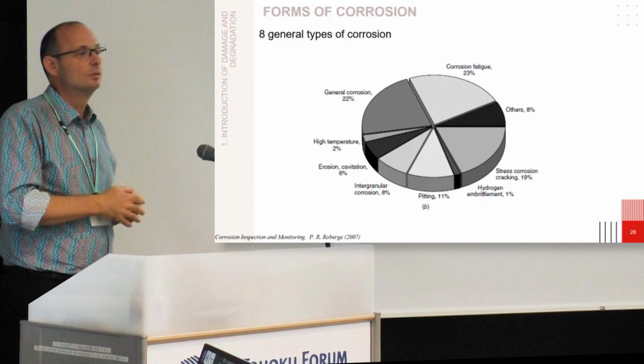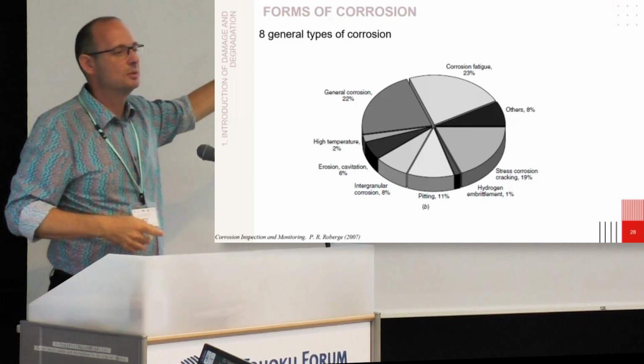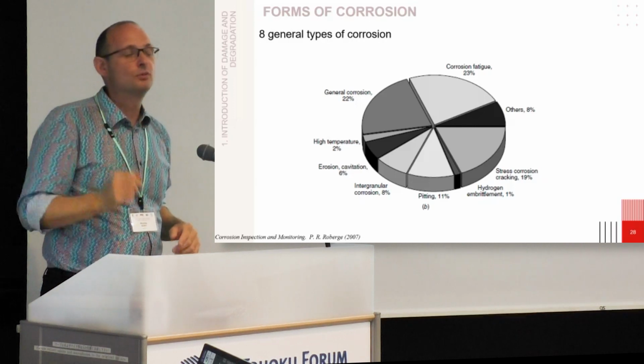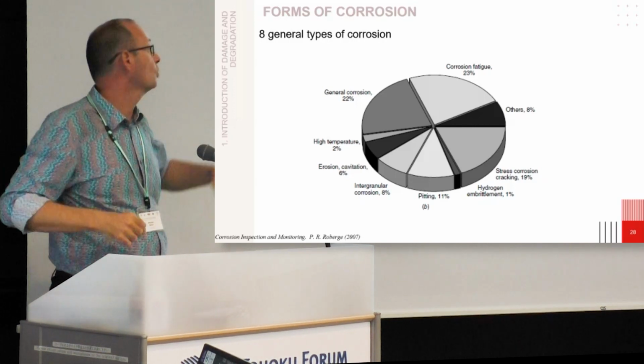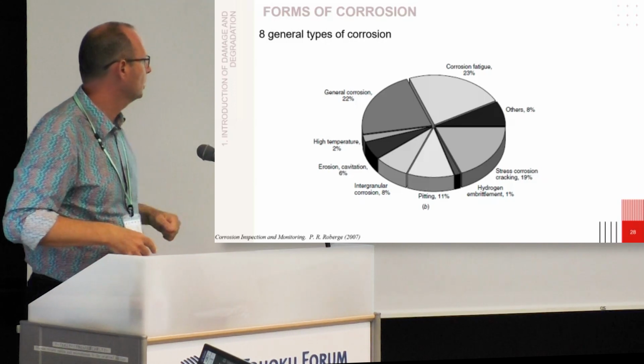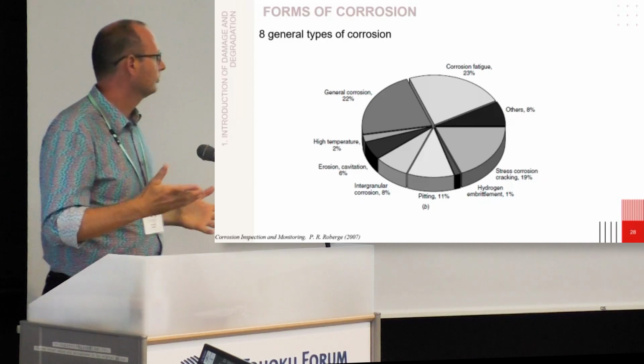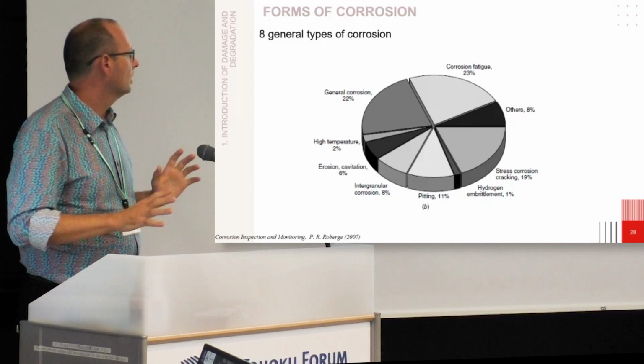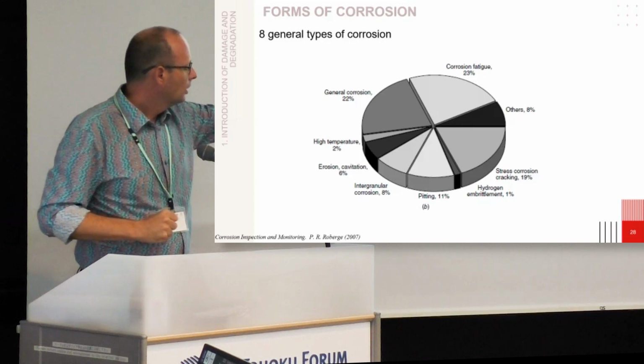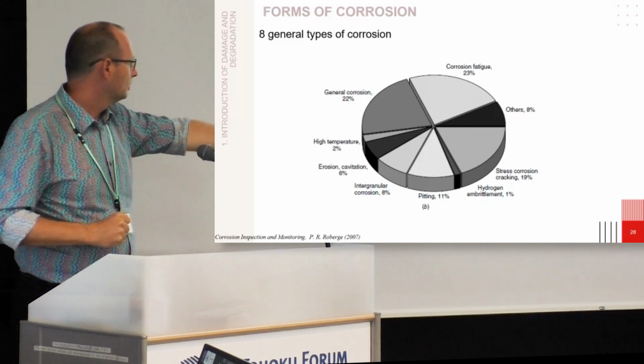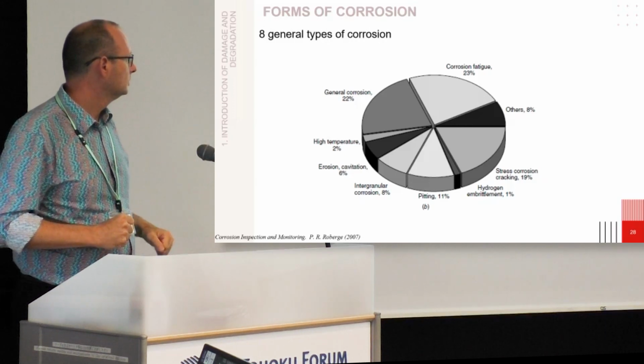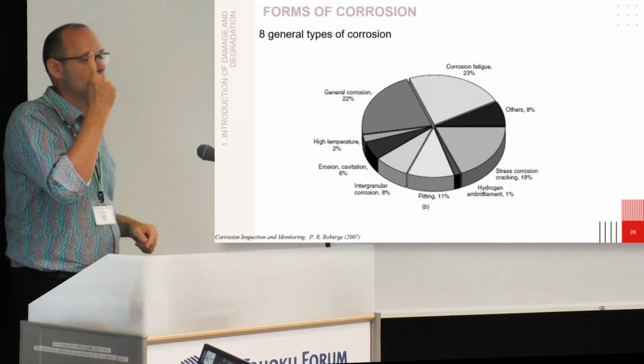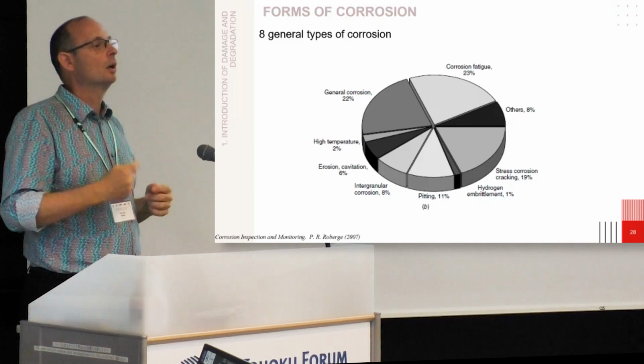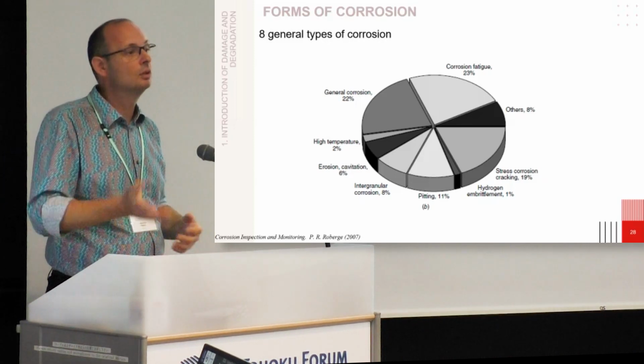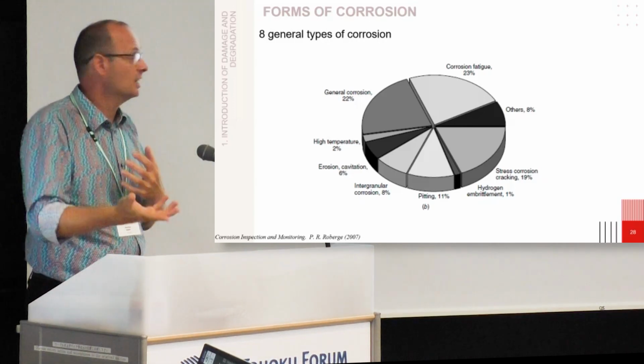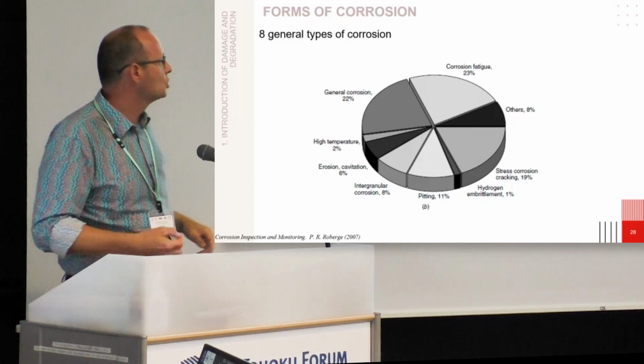General corrosion, so that's the largest one. And if you remember the few examples that I chose in the slide, most of them were general corrosion. There is a little bit of high temperature, and the others are mostly divided in the same value. One point: at the time the graph was done, hydrogen embrittlement was only 1%. Most hydrogen embrittlement comes from the oil and gas industries. But nowadays, with the evolution of hydrogen energy, we are expecting that hydrogen embrittlement will increase.